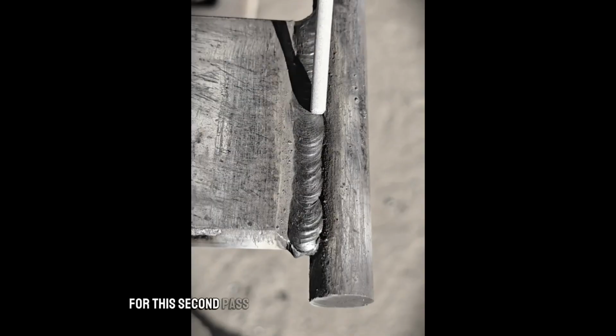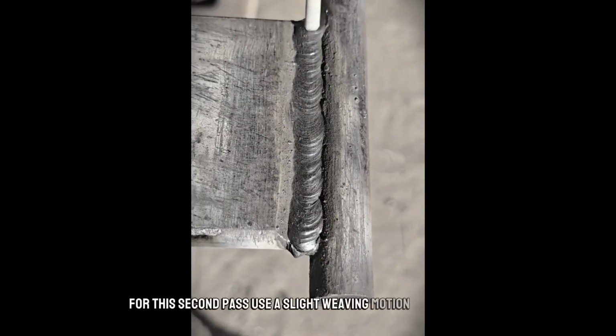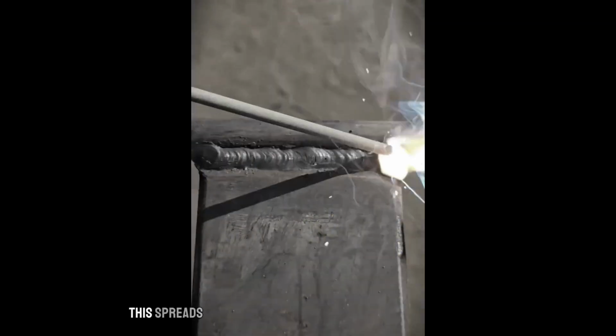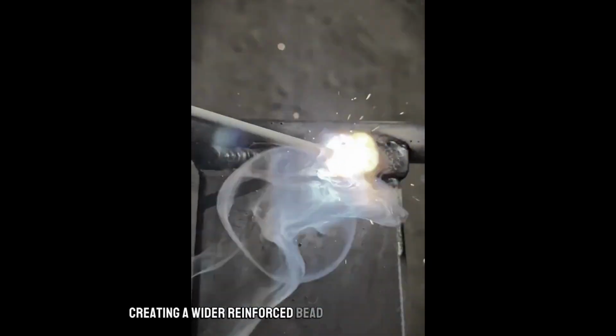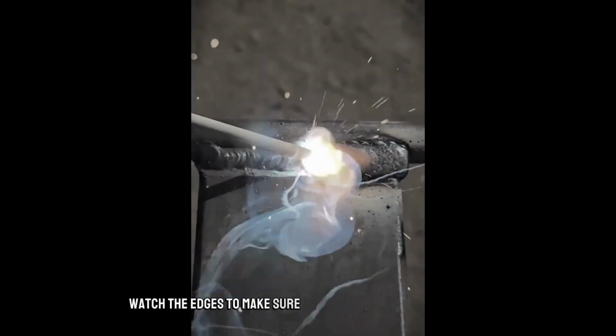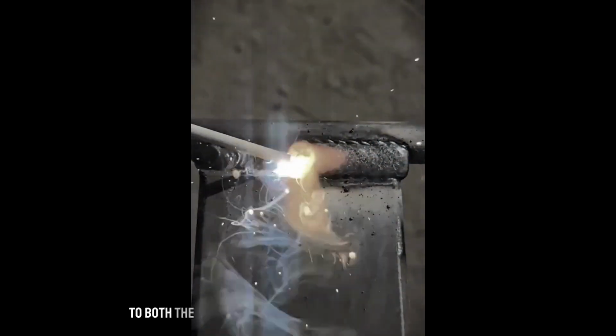For this second pass, use a slight weaving motion with the electrode. This spreads the molten metal across the joint, creating a wider, reinforced bead. Watch the edges to make sure the metal is wetting in properly to both the rod and the plate for a smooth, professional finish. And there's the final result.